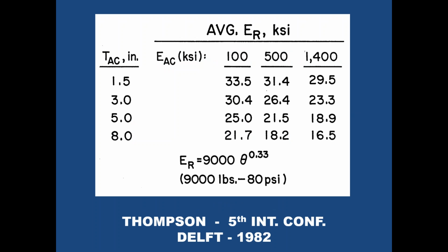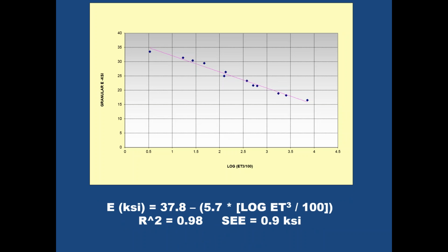Now this is work that I submitted in a discussion at the 5th International Conference at Delft. We looked at various asphalt thicknesses, modulus of the hot mix. This is a particular value, that modulus of 9,000 theta to the 0.33, that's a reasonable representation of the AASHTO road test base course. Some work we did, repeated load testing on that. If you plot this up and look at the granular base modulus as a function of ET cubed, what's the stiffness of a beam? ET cubed, something like that? Pretty close? Okay. If you look at log ET cubed over 100, where E is in KSI and T is in inch, and plot that against the granular base modulus based on that previous data, this is what you get.